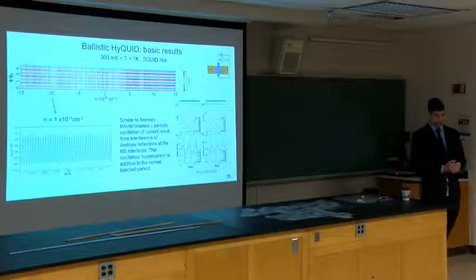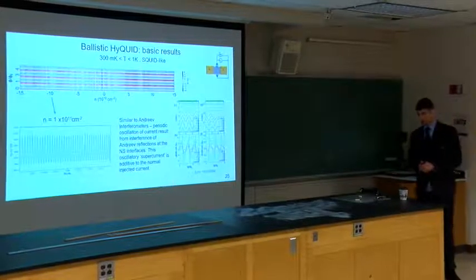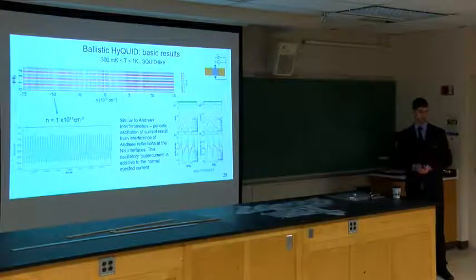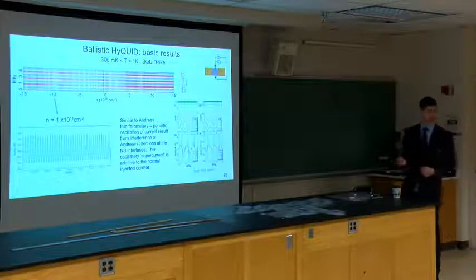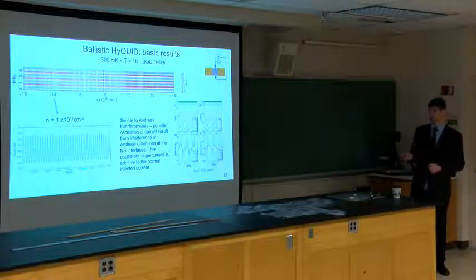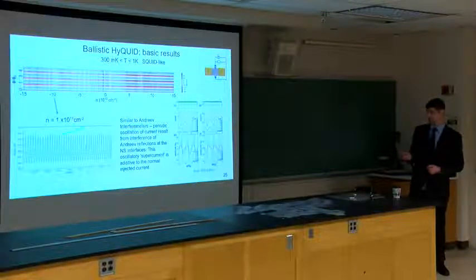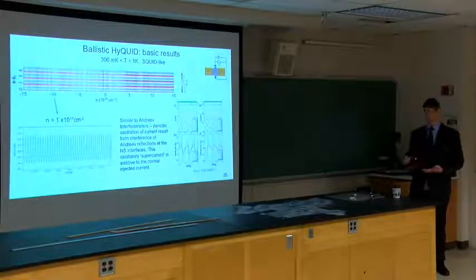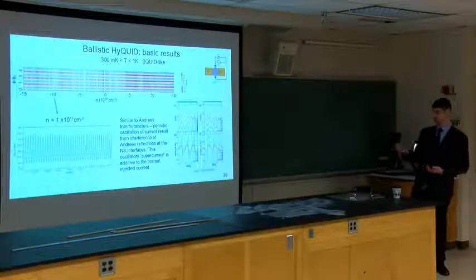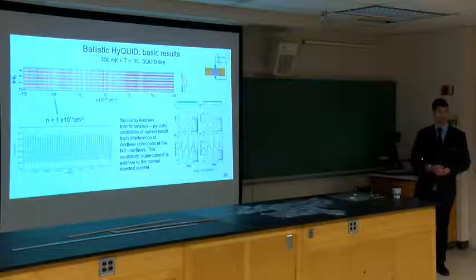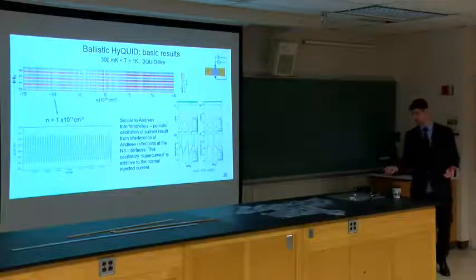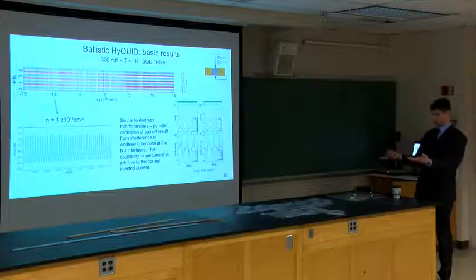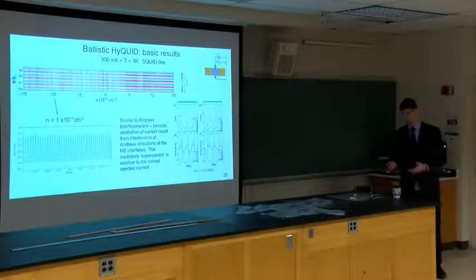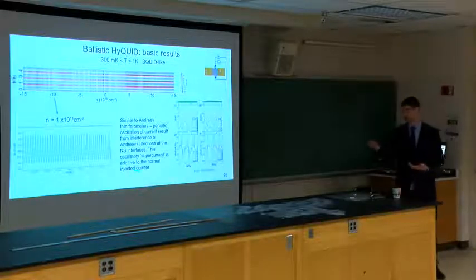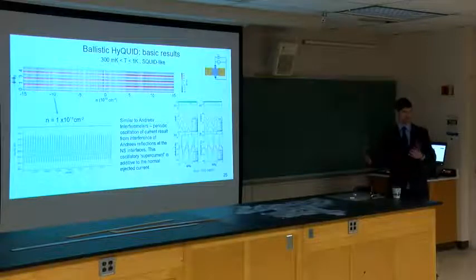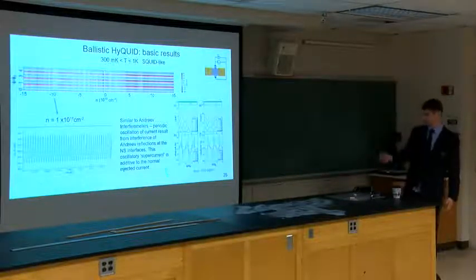So what happens? As I showed in the squid example earlier, we get something that looks like a squid, except it's not superconducting, because the resistance here is not zero. We're measuring between normal contacts. However, the effect of these contacts is inducing an oscillatory resistance as a function of the superconducting phase difference across the two contacts. So it's similar to an Andreev interferometer. At this point, we can't say a whole lot more, but the oscillatory supercurrent is basically an additive component to the normal resistance. There are a few more details if you want them later, but it looks similar to a previous diffusive case.